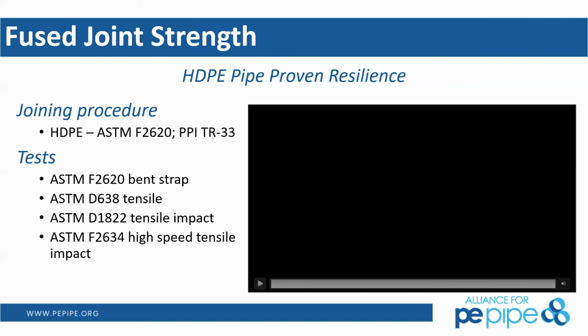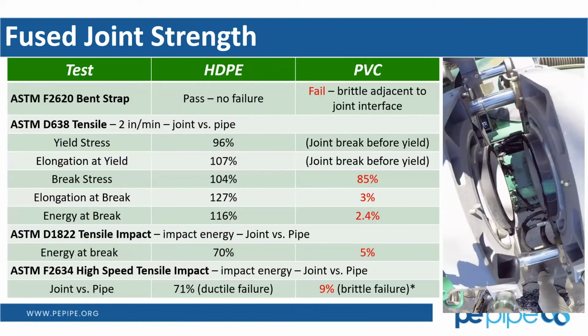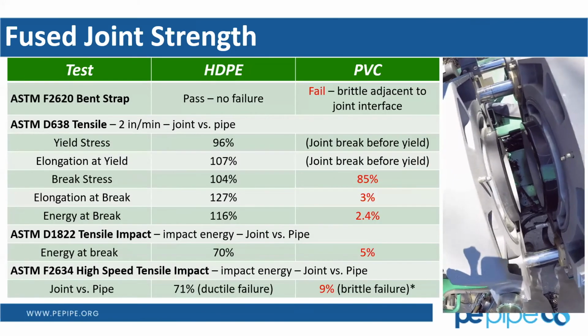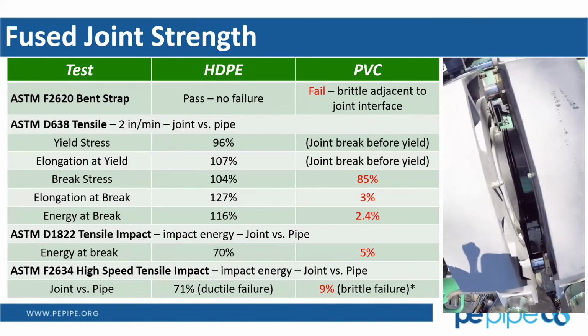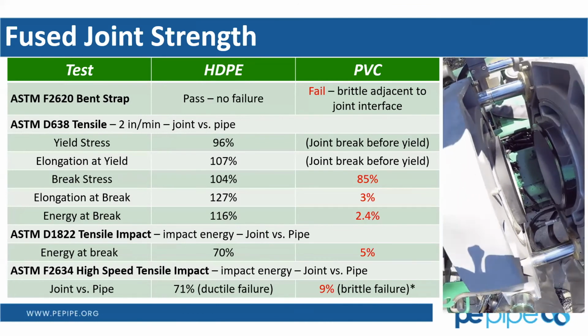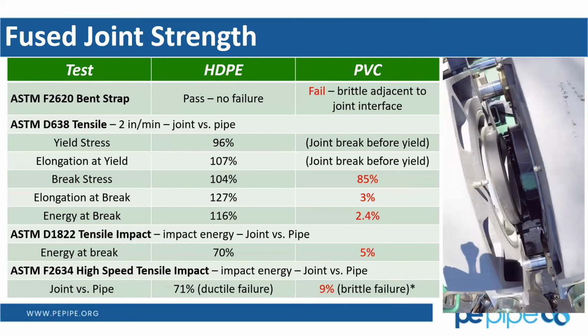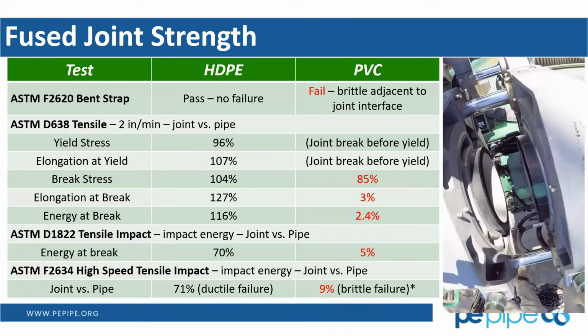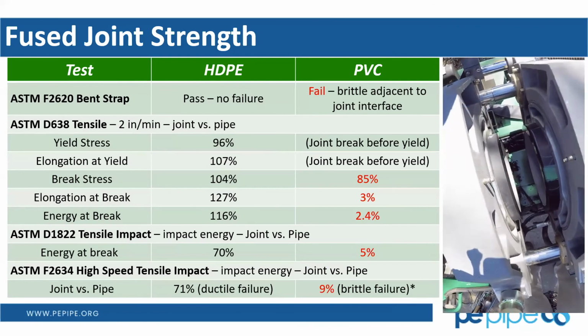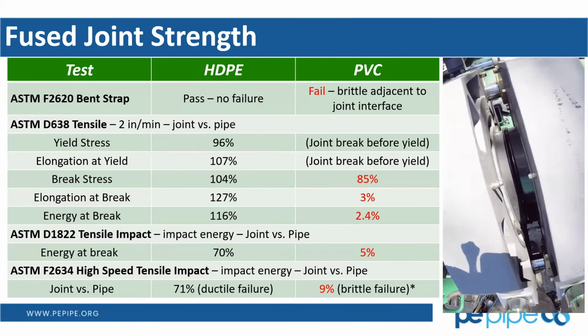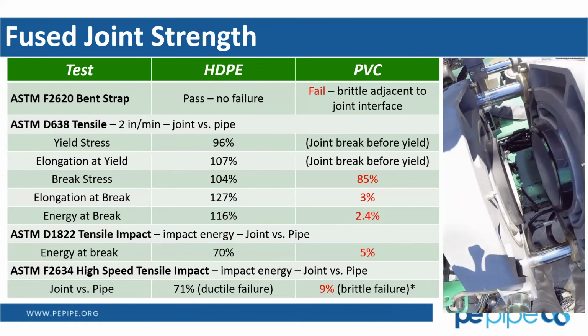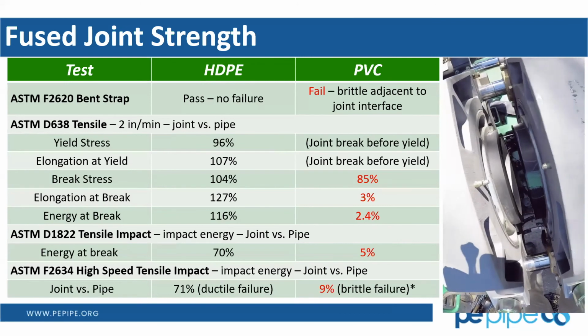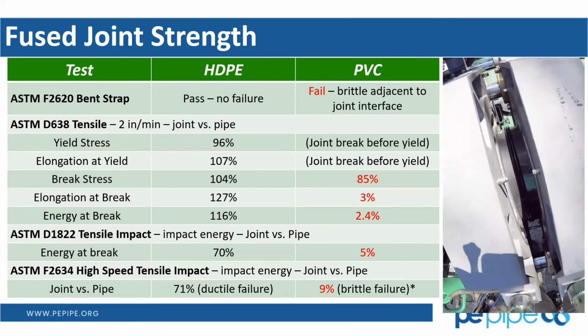Stephen, you had a question? Yeah, Dustin, we had a question in the Q&A section talking about the differences between HDPE and, specifically, fused PVC. That has a broad range of answers, but while you're showing this information, I think it's very important to note that a heat fusion weld by polyethylene and one by PVC results in a very different joint. They may look the same, they may use similar equipment, but molecularly, the polymers don't join the same way. That's why you said that a joint of polyethylene, fused the right way, gives you a joint as strong as the pipe. In a PVC butt fusion failure, it's not as strong as the pipe, and there's very specific reasons for that. So everybody needs to be careful with that. Make sure you look into it and do your due diligence to make sure you're getting what you think you're getting. Yep, that is exactly correct.